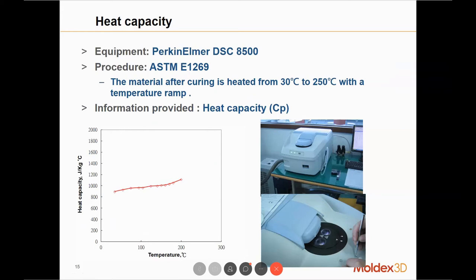And then during the cooling stage, the thermal properties become very important. So we'll be able to test the heat capacity and also the thermal conductivity. For heat capacity, we also use the DSC 8500 under the procedure ASTM E1269. So an already cured material will be heated up from 30 to 250 degrees Celsius, also at a constant heating rate, and then we will record the whole heat flow. By that, we'll be able to know the heat capacity, the heat that is actually absorbed by a certain amount of material, and get the heat capacity property.